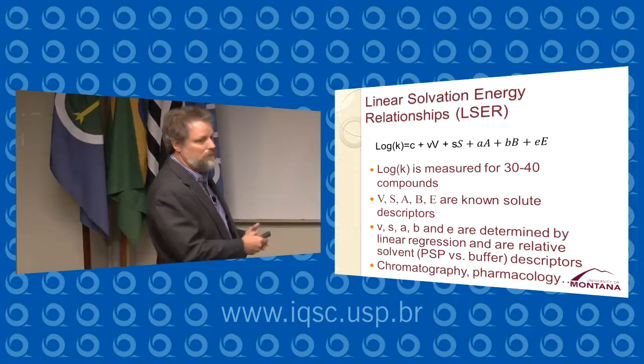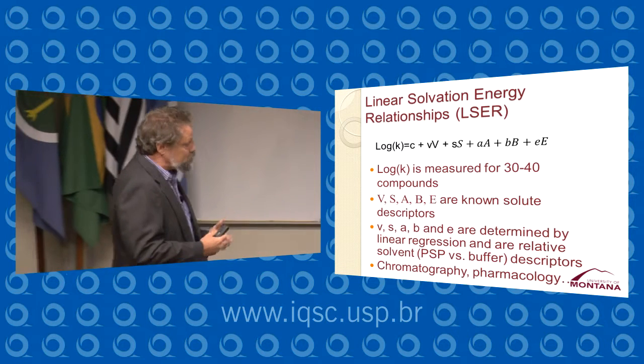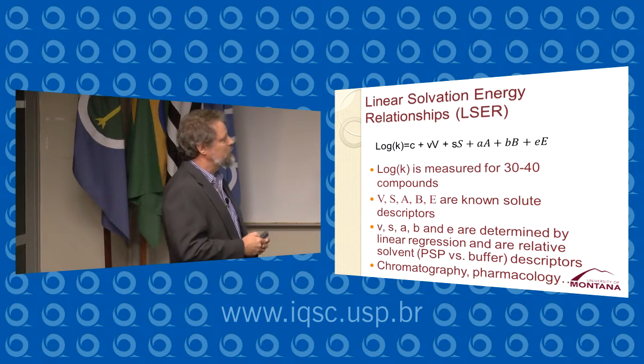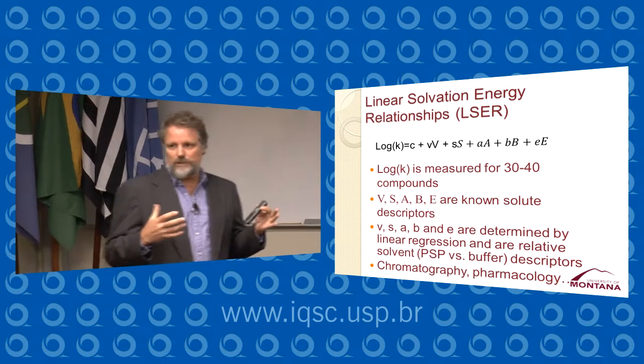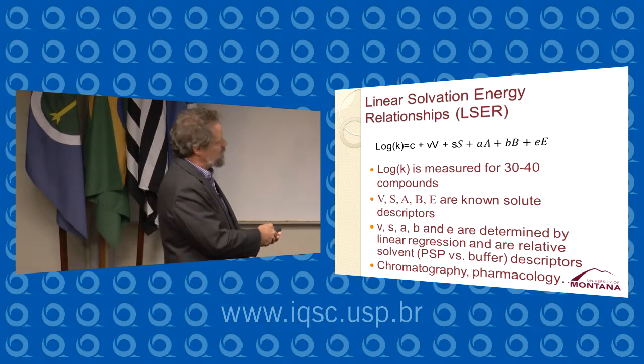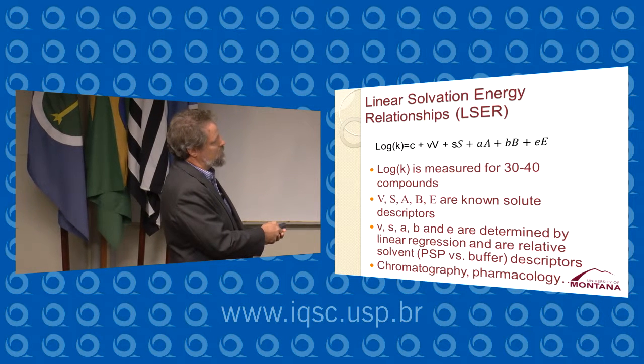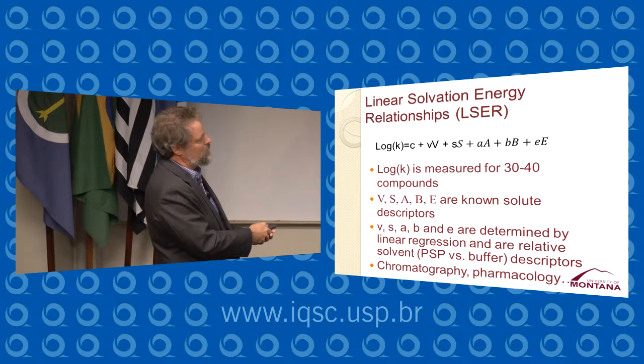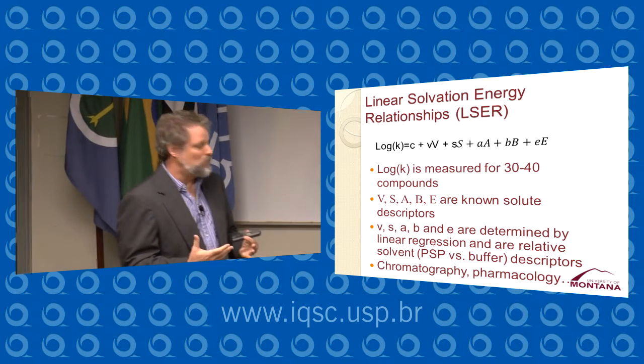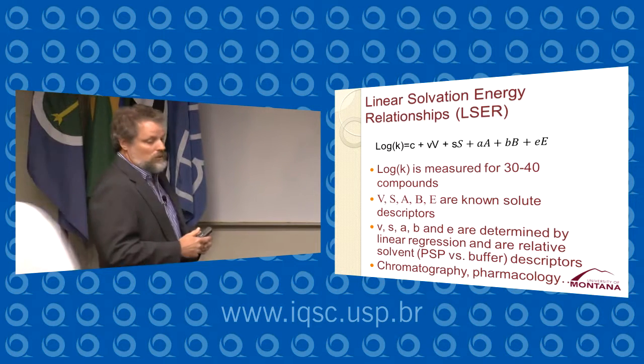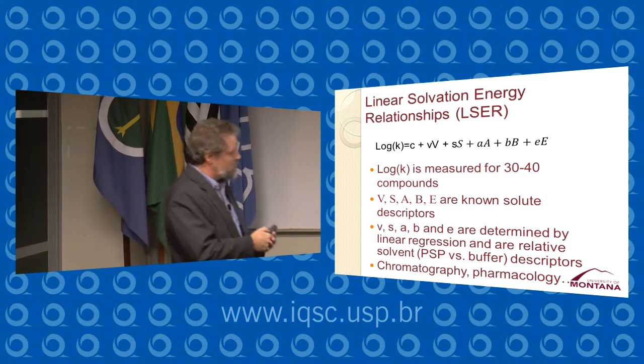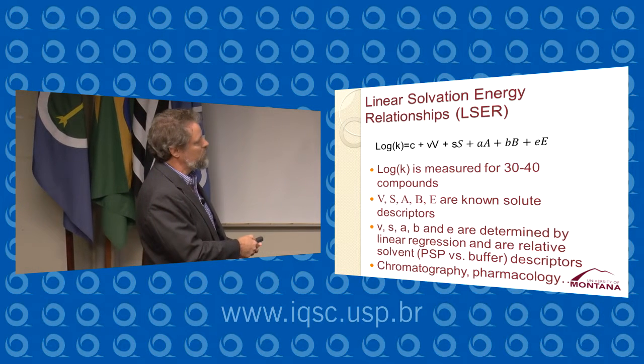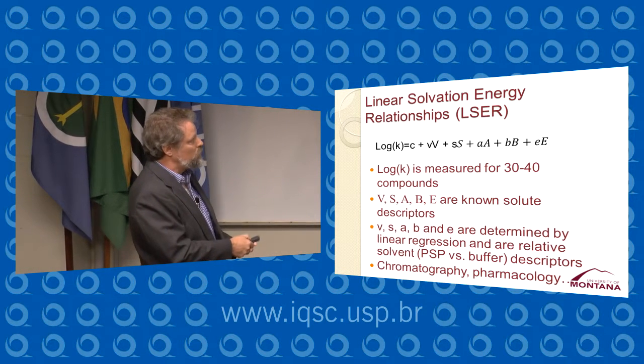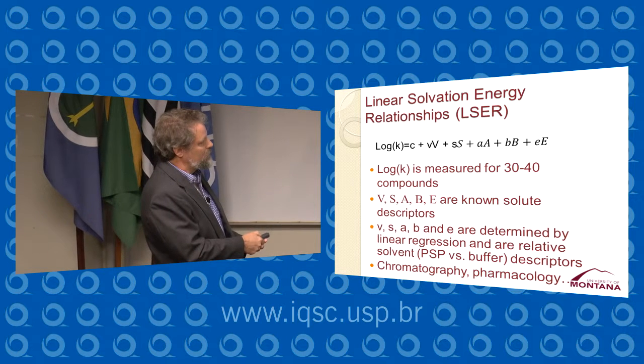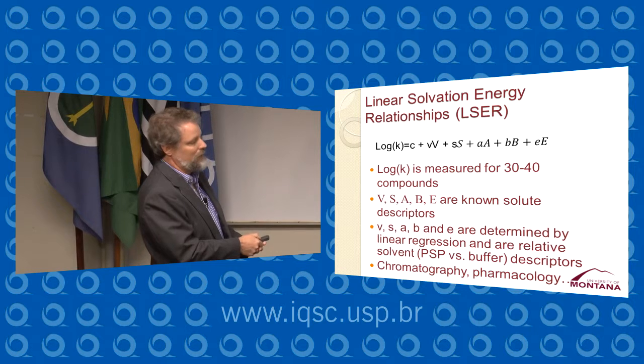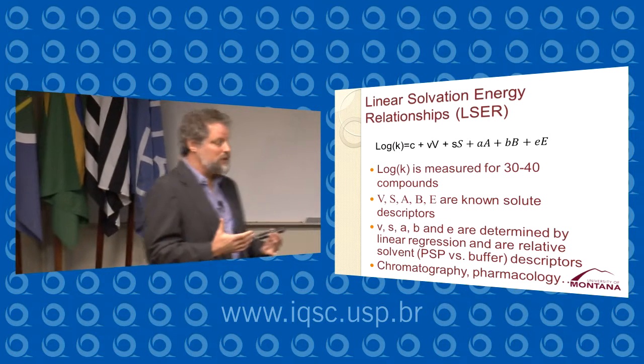So this is a volume term. It's the volume of the analyte, the specific molar volume of the analyte, and it speaks to the types of dispersive interactions you might expect to have. This is a polarity term, this is an acidity term, a basicity term, and then this is a polarizability term. It's the excess molar refraction of the solute. So the way we apply this technique is we measure the retention factors and calculate the logarithm of the retention factor for 30 to 40 different compounds, for which we know the values of capital V, capital S, A, B, and E. We know those values, they're tabulated, they're published.